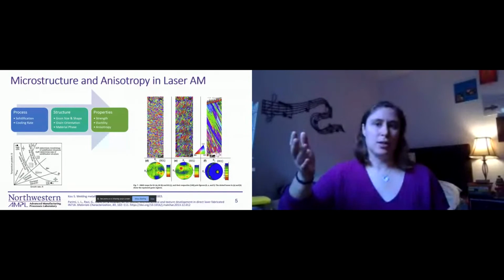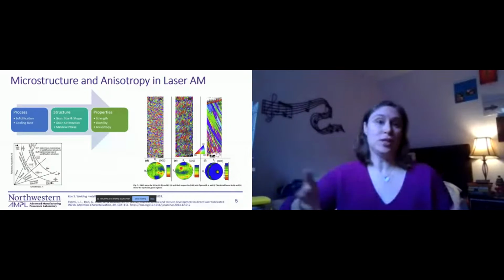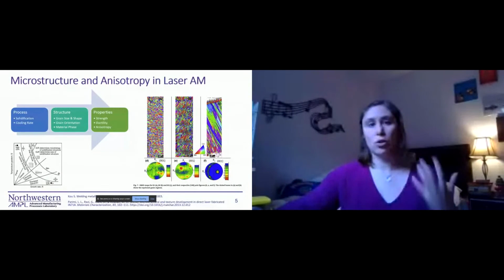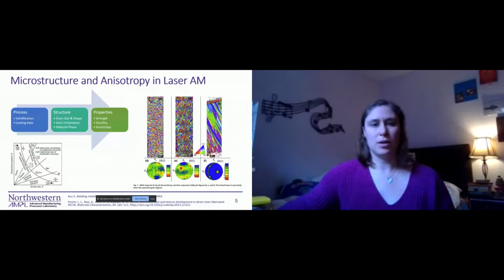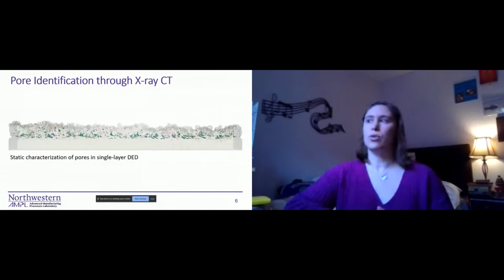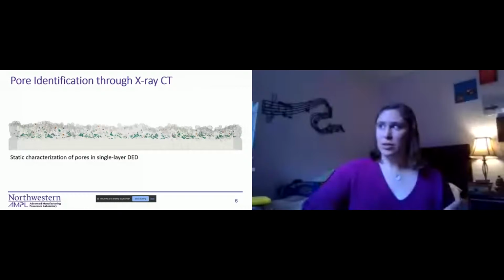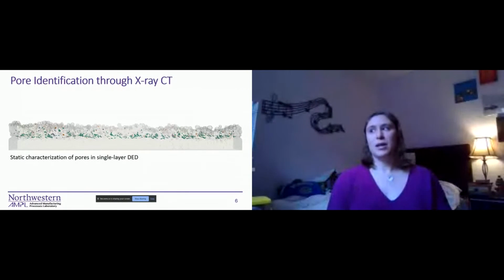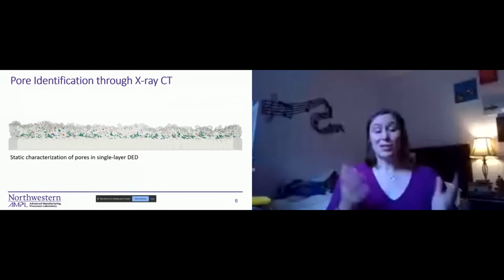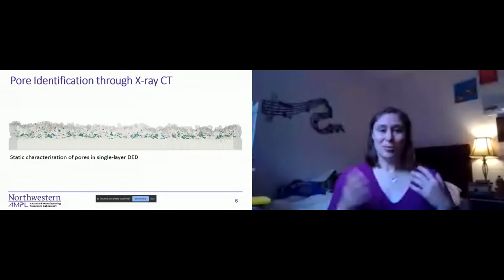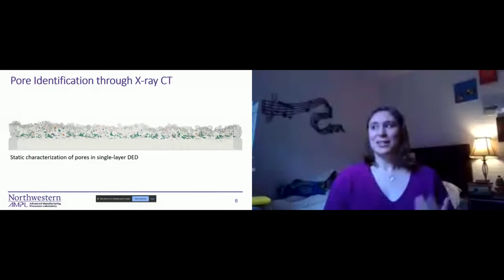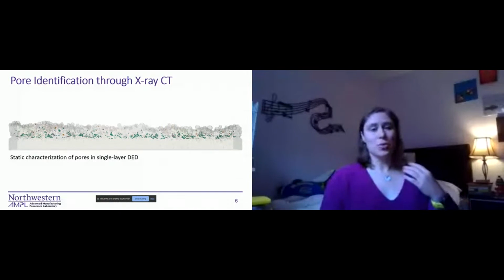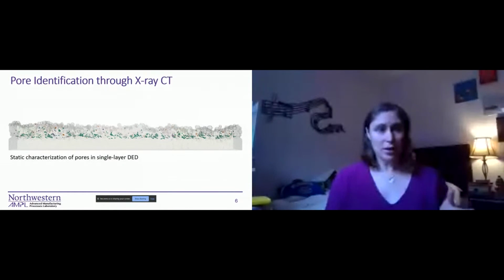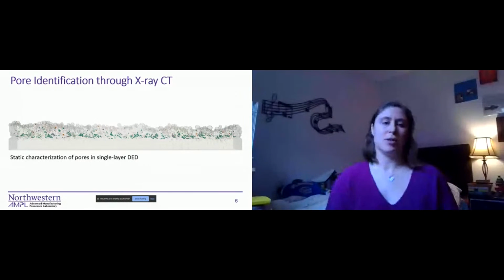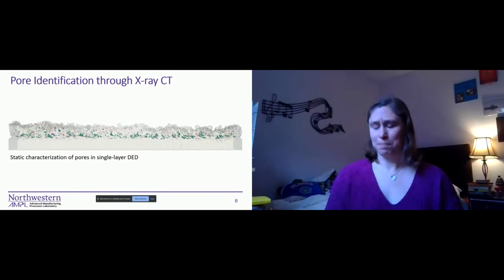So anisotropy in AM has been a unique issue that people have been researching. There's also very unique structures in the shape of pores. Pores are one of the most common things that are removed or post-processed in metal AM. This costs a lot of time and money, not to mention critical material failure in load-bearing situations. The vast majority of pore characterization is just through X-ray CT, and I've shown an example here of pores that are in a single layer DED part.